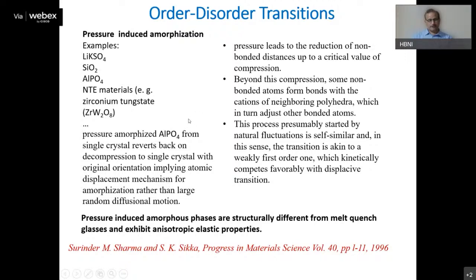In these cases, when you apply pressure, you get amorphization. And there is one case of AlPO4 where if you take a single crystal of AlPO4 and apply pressure, it goes to an amorphous phase. But on release, it comes back to the crystalline phase with the original orientation. So it shows some kind of memory effect. So the atomic displacements corresponding to this order-disorder phase transition are somewhat small, which leads to this.